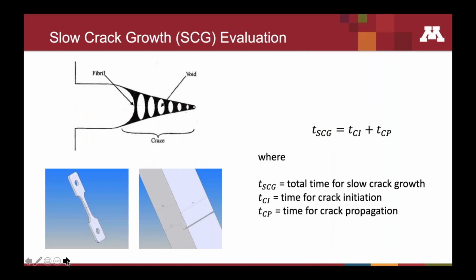So the way that this works, the stress cracking mechanism basically has been assessed historically in the corrugated pipe industry by doing these types of notched tests where we put a small notch in a test specimen. We put some constant stress or load on that specimen. We put that coupon, the dog bone specimen that you see there in the lower image, into some test bath at an elevated temperature to accelerate the failures, and then we wait for them to crack and fail.